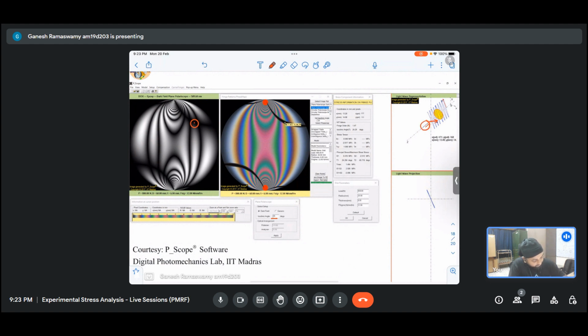The response is nearly zero, which is why I see a black point. If I see the same thing in color with a white light source, this point is still black, which implies that this is a function of direction and not the wavelength. So this is what the isoclinic is about.